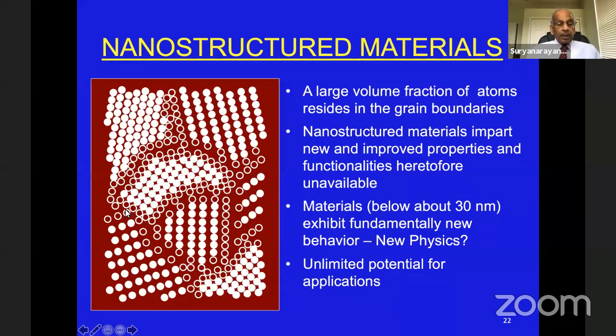But the most important thing is the nanostructured materials. The important point is very small grain size. If I look at this, it does not tell me anything about the nature of the material, except when I see the nature of the grain boundaries. The grain boundary atoms are many more. That means it's a nanocrystalline material. Whereas if it is a coarse-grained material, the number of atoms in the grain boundaries will be much less than what they are inside the grains. And this large volume fraction of atoms residing in the grain boundaries is the factor which will determine the interesting and very important properties of nanostructured materials.